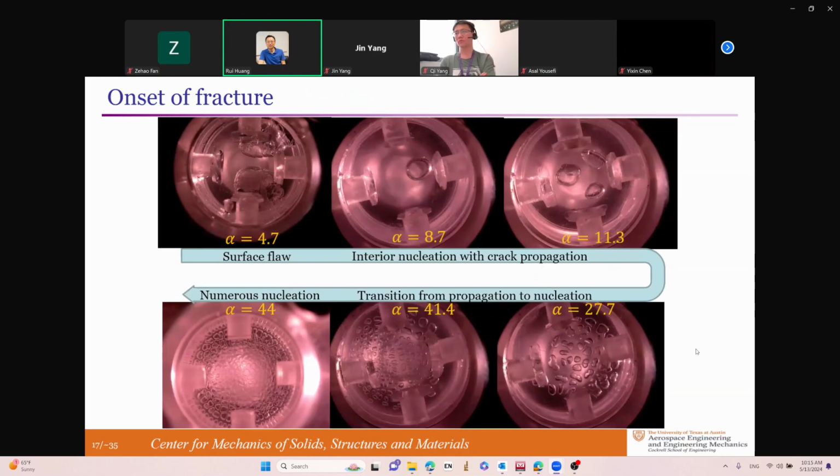All right. So that's what goes on as a function of the thickness. The thickness is the only length scale in this macroscopic problem, right? As the thickness changes, the confinement changes, so the ratio of the hydrostatic tension to the shear energy changes, and therefore you see different response behavior. Surface nucleation when the thickness is very large, one crack dominating when the thickness is a little bit smaller, 3 cracks, 100 cracks, 200 cracks, depending on the thickness.